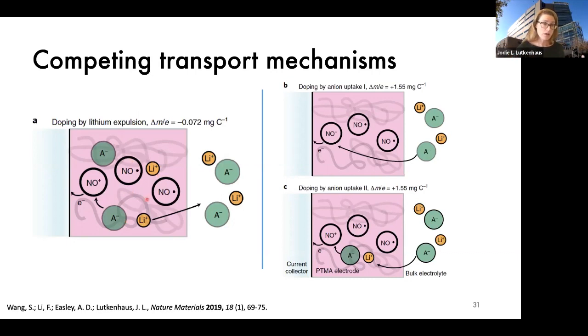And so when we have a doping event, two things could happen. One is the anion, which is already there because the polymer is swollen with electrolyte, is in the close vicinity and immediately dopes the oxoammonium cation. That leaves this lithium cation unmarried. It doesn't have a place to go, so it will diffuse out into the electrolyte to maintain electroneutrality. If that occurs, then the delta M/Q value would be based solely on the transport of a lithium cation leaving the electrode, so it would be negative and a small value. In the other case, if the lithium cation doesn't diffuse out, an anion can still come in from the external electrolyte to pair up there.